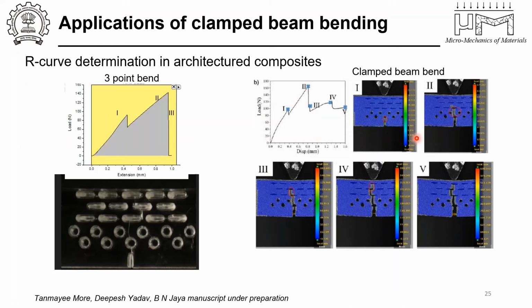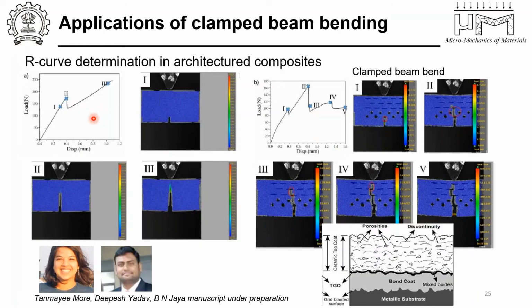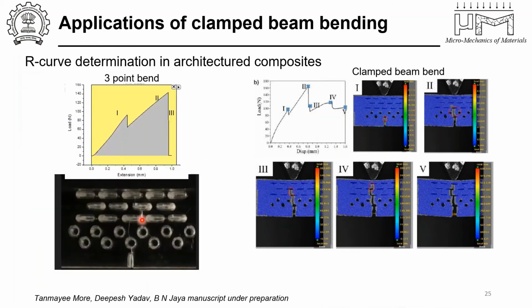And I could not measure this very clearly when I did a 3-point bend test. So when we did a 3-point bend test, the number of load drops is much less. In fact, it looks pretty similar to what a monolithic material would look like. And that's because this geometry is not stable, whereas the clamp beam bend is a very stable geometry. So I can record each of the load drops, and each of those load drops corresponds to the crack moving to the individual features, and that can be recorded, and the R curve can be later determined.